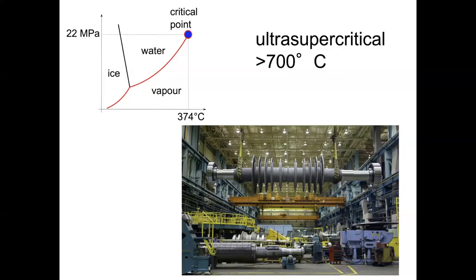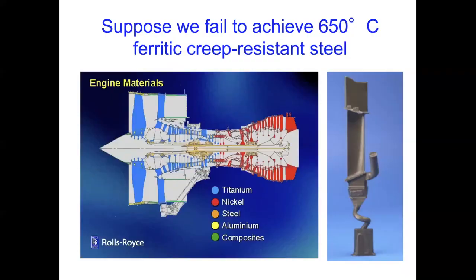Now, we could use austenitic stainless steels. The problem is that the thermal expansion coefficient of austenite is much bigger than ferrite, and therefore you get failure from thermal fatigue because the temperatures are not constant, okay? So we need another alloy system, okay? And of course, we can cope with higher temperatures in it.